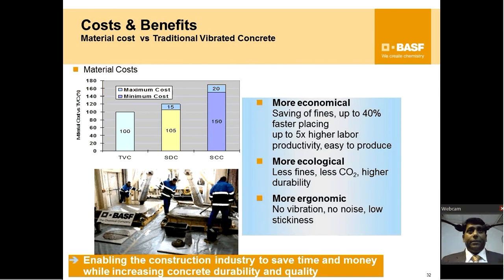So what you're saying is, you use the traditional vibrated concrete, and if you add your admixture, it will transfer it to a smart dynamic concrete? It's not exactly the same mix design, a little bit of change in the mix design. For example, in your mix design, your coarse aggregate versus fine aggregate ratio is something like 60-40. With a self-compacting mix, it could be something like 55-45 or 50-50. A minor change in the mix design, but the overall cementitious content and others will remain the same. Same aggregates, nothing different. Same cement, maybe a little bit of change in cementitious content, it all depends upon the sand and other things. A little bit of change in the mix design, you get M30, a highly flowable mix and an excellent concrete.